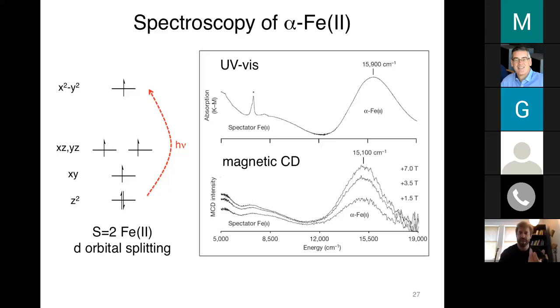So moving back to MCD, again, by looking at the response of this MCD feature of alpha iron, how it changes with respect to magnetic field and temperature, we were able to understand the nuclearity and spin of this species based on its magnetic properties. And we found that it was a mononuclear S equals 2 site based on this.